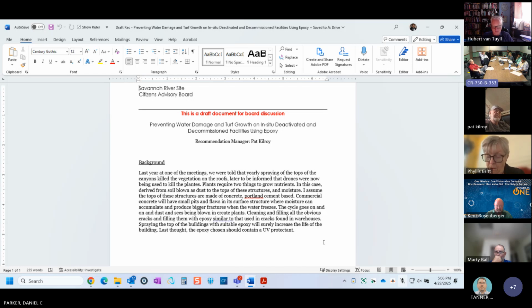The concrete that was used for the roof slabs and for the caps is a special concrete. It's the site 4000 PSI concrete that's been modified with shrinkage compensating admixture. It's got integral waterproofer in it, which reacts over time to seal small cracks up to 50 micrometers in width. This material doesn't hydrate to seal large cracks like an inch or half inch or even a quarter of an inch.